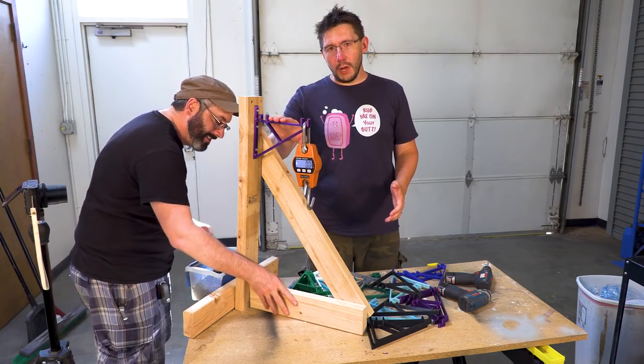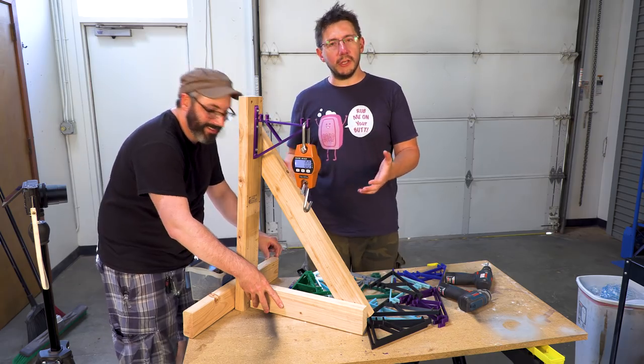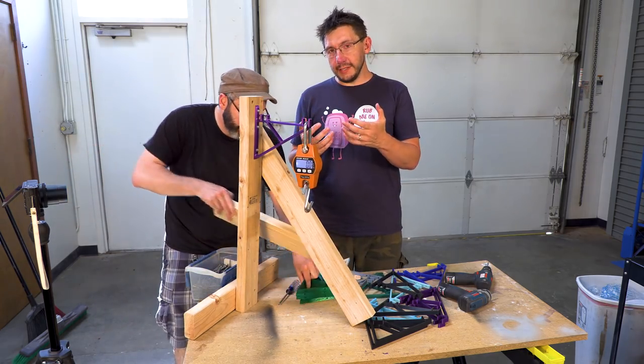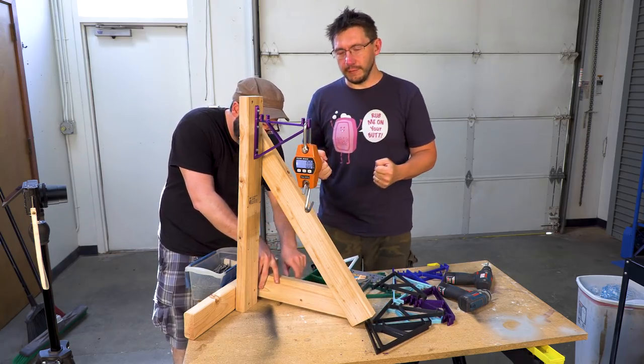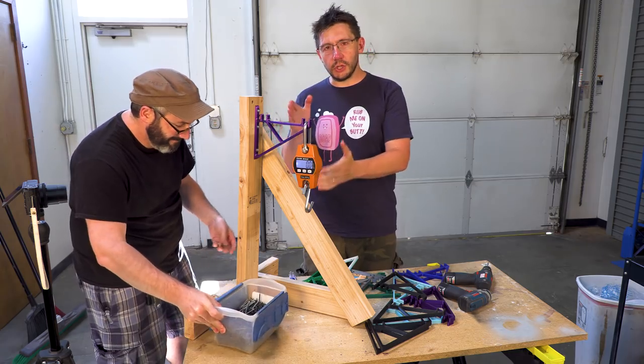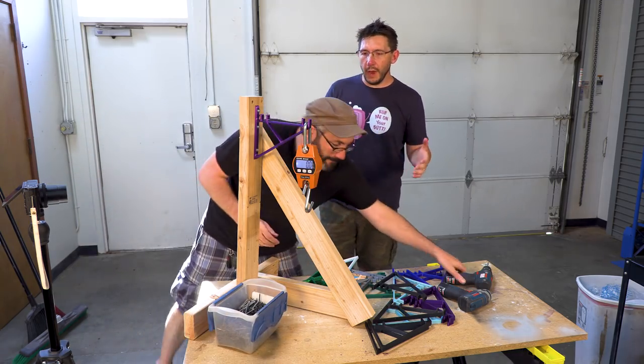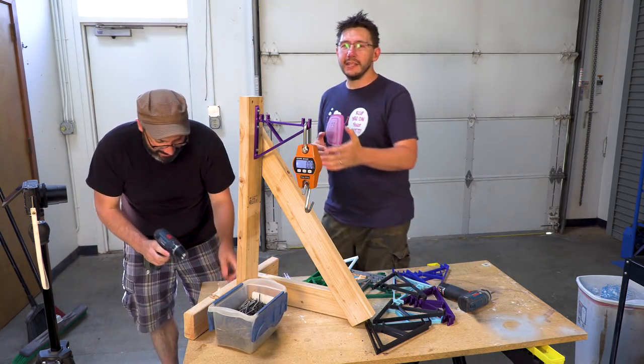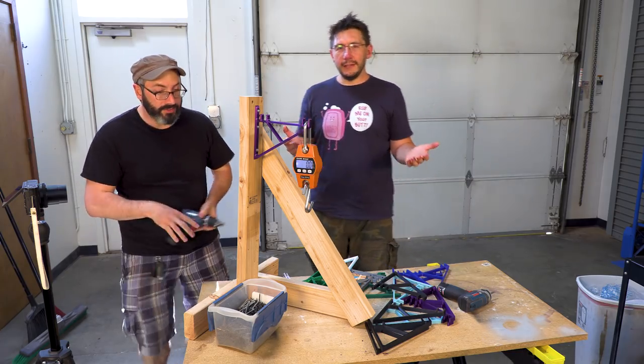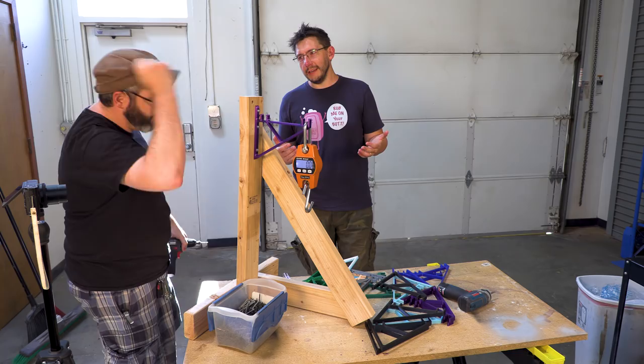This bracket, Polyalchemy Elixir, which is essentially solid plastic, I was able to put 70 pounds of downforce on it, and the wood was giving way. The screws into the wood were giving way before the plastic was even really bending. Okay. And we also should put some sort of padding down here because you're going to smash your thing.